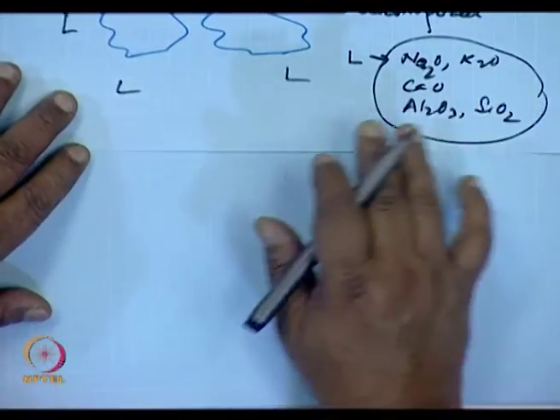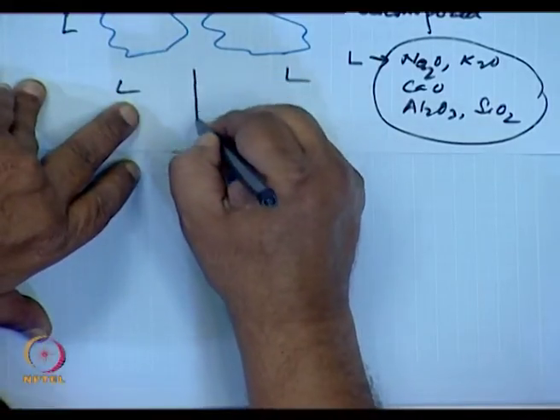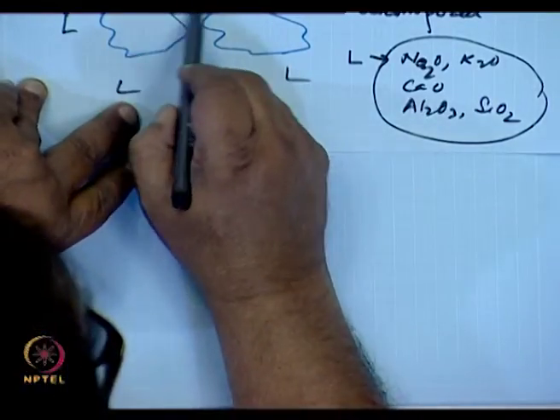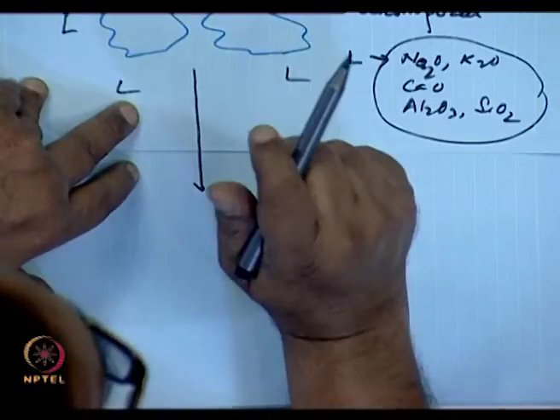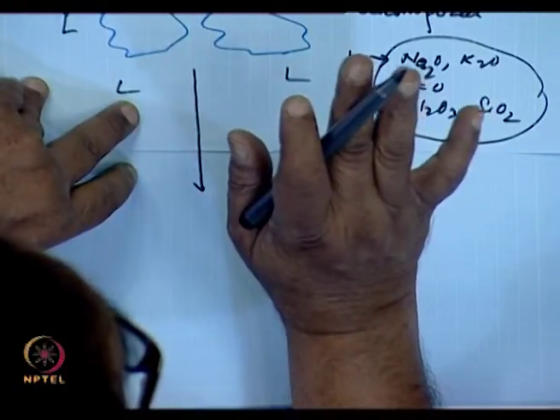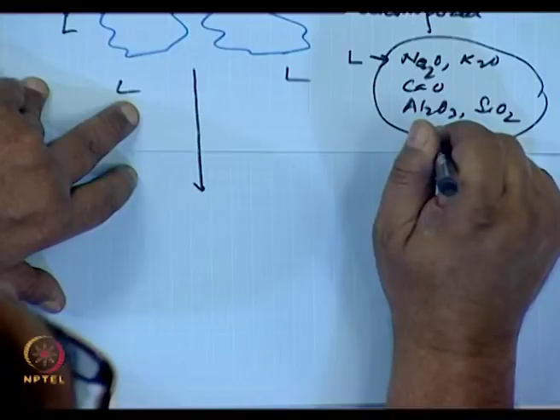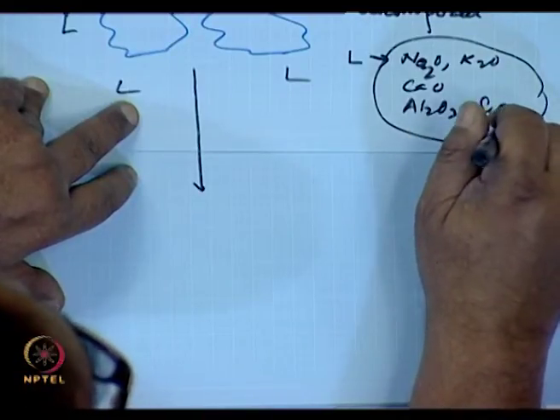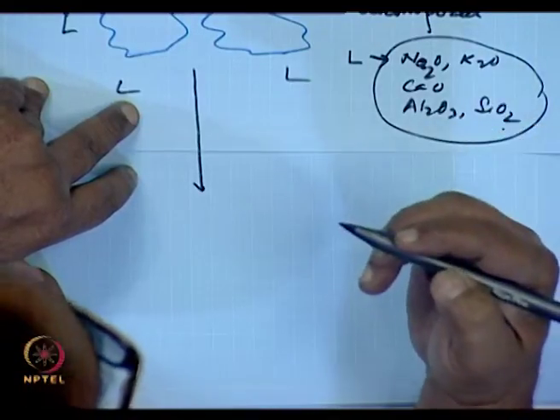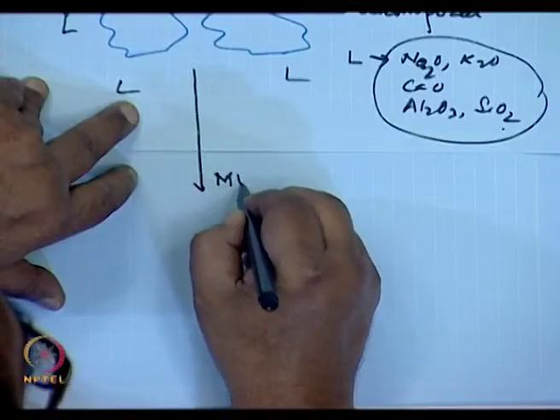As the temperature increases more, with more sintering, what happens is something like this. This liquid, as the feldspar has dissolved totally, it has reacted with the kaolin contents and the clay contents, and the liquid has become richer and richer in alumina and silica. It becomes very saturated with a particular product called mullite.